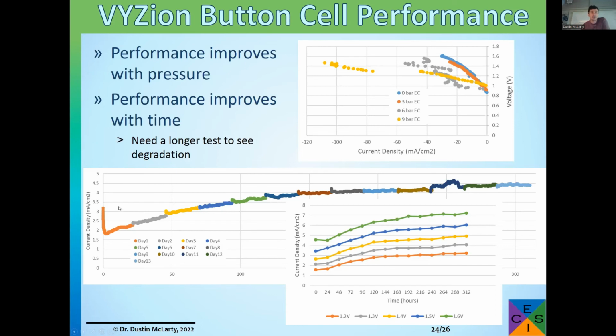The other main thing to highlight, we did a 2-week test, and during those 2 weeks, it was still improving, still in that initial conditioning phase. So it's not a material that breaks down and degrades really quickly. It's got some longevity to it. We don't know yet if it's going to be the 8 to 10 years we need, but it's got some promise there for durability.